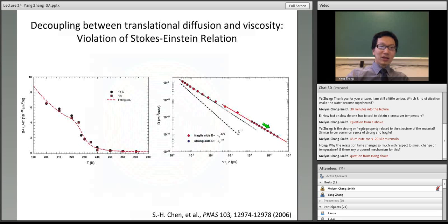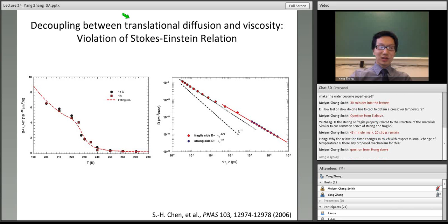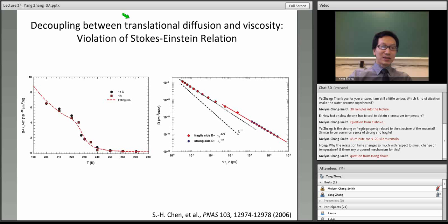The decoupling also happens between the translational diffusion and viscosity. The relation between the translational diffusion and viscosity is the Stokes-Einstein relation, which is based on hydrodynamic continuity. At supercooled temperatures, because of these cooperative motions, the Stokes-Einstein relation also breaks down. This is work by Professor Chen in 2006. He measured relaxation time and also diffusion coefficient and tested the Stokes-Einstein relation. The result is very amazing because it demonstrates clearly that at the crossover temperature, the Stokes-Einstein relation breaks down. Again, it's at the crossover temperature, not at the glass transition temperature. So many things have already happened above the glass transition temperature.